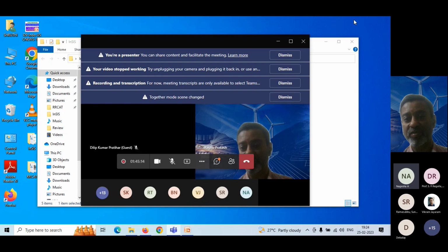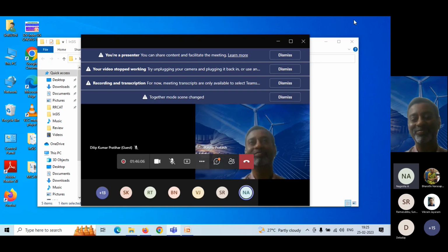Okay, the second part of his question was related to the initial crack size of 1 grain that I have taken. It's normal practice to take the initial crack size as 1 grain diameter if you don't detect the presence of any crack. Because the grain itself is a kind of defect, the initial crack length is taken as equal to the grain size. That is the reason why we have assumed it to be the grain size.